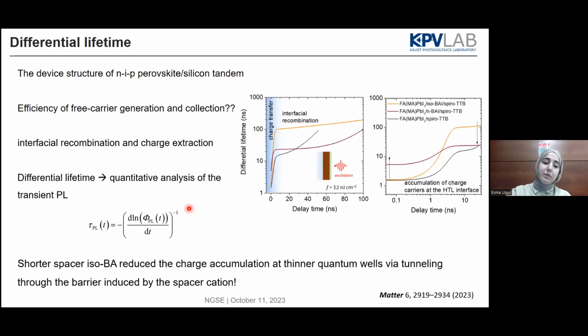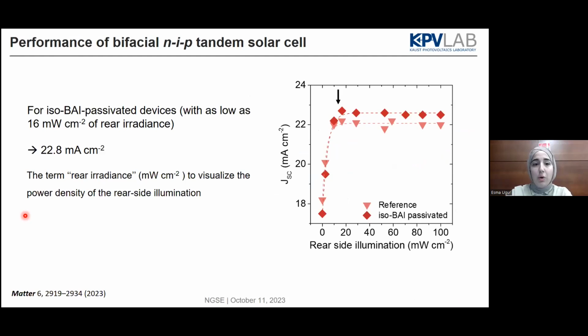So what we can say here is that isobutylammonium is a shorter spacer than N-butylammonium. Therefore, it reduced the charge accumulation at these thinner quantum wells through tunneling, via tunneling through the barrier induced by the spacer cation. So how did the performance turn out at the end? For this one, we can get higher current density compared to the control. The N-butylammonium-based one was not working as well as the isobutylammonium, and we get a higher open circuit voltage as expected.